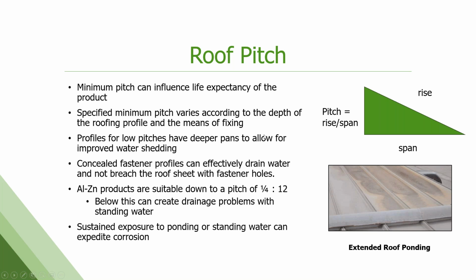So minimum pitch can really influence life expectancy. We don't like to go below 1/4 in 12, so you've got to have that or above. Profiles for low pitches should have a deeper pan, which will allow for more water shedding and help eliminate any pooling that might occur. And concealed fasteners are really the way to go. You're going to get more effective water drainage, and you're also not going to have anywhere where water can breach to the underside of that installation. So again, you can go down to 1/4 in 12. Below that, you're going to have drainage problems.